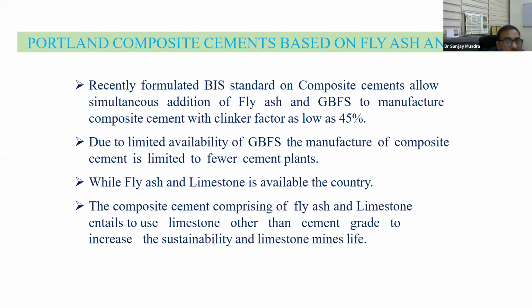Then Portland composite cement is another that we have done in research with the use of fly ash and GGBS. This is another ternary blend. Recently formulated BIS standard on composite cement allows simultaneous addition of fly ash and GGBS to manufacture composite cement with clinker factor as low as 45%. So we have already reached the level of 45%. Our target is 35% or 30%. So we can reduce the CO2 emission in the next 10 to 15 years.